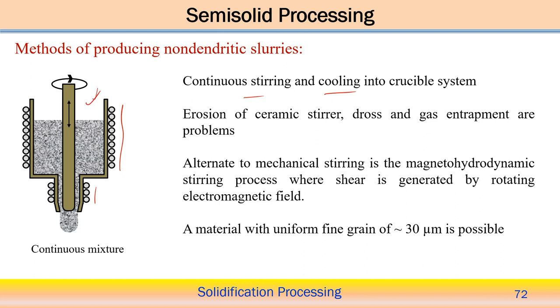So, here molten metal is put in, at the same time a stirring action is going on, and it is allowed to cool, or that cooling can be controlled, in other words the rate of temperature change is controlled, and then the semi-solid comes out from here. But there are some issues or difficulties associated with this particular process. One problem is the erosion of the ceramic stirrer. This component is usually made of ceramic, so erosion might occur, and it creates some dross and gas entrapment, because we are stirring.